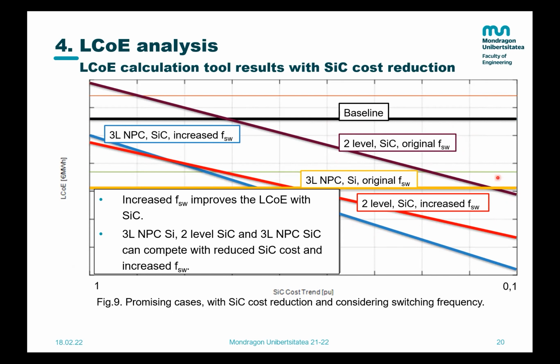We see that increasing the switching frequency with silicon carbide can improve the LCoE of the original switching frequency. This is because, as I said, the silicon carbide is good at switching, so it keeps high efficiency even at high switching frequencies. High efficiency means high energy output. And with increased switching frequency, you can reduce system components, such as the filters, for example, right? So the LCoE will be improved with increased switching frequency.